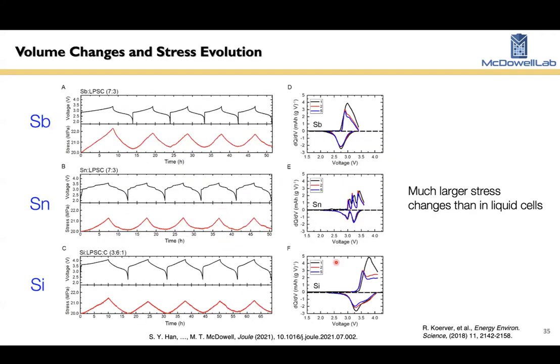So these alloy anodes, one of the distinctive things about them is that they undergo very large volume changes during lithium insertion and extraction. This is because they have very high capacities. They form new phases that are very rich in lithium. So we did a study a few years ago where we were measuring stress changes in solid-state battery cells with different alloy anode materials. These are data from this paper. We were exploring antimony, tin, and silicon.